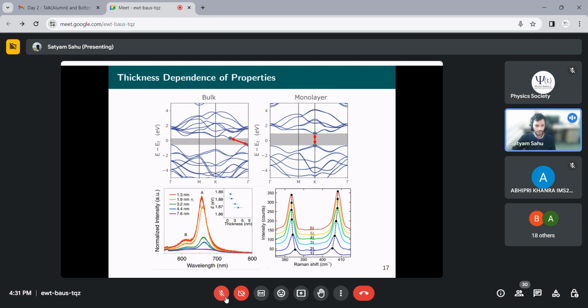If we see here, the red color one, which is for the monolayer MoS2, has very high emission. But as you start to increase the thickness, the emission is decreasing crazily, and for something like 5 to 10 layers, there is almost nothing at all.